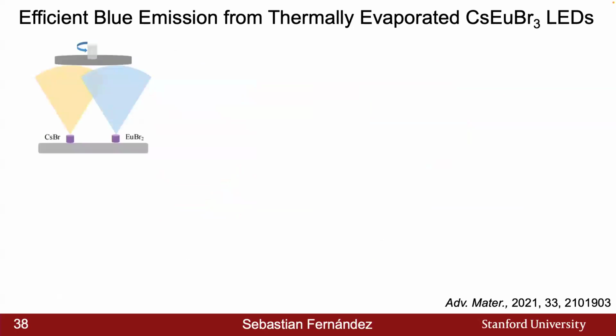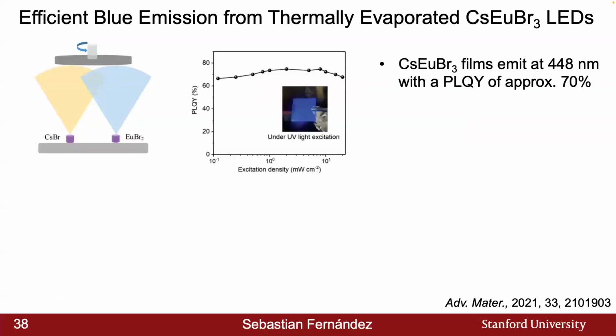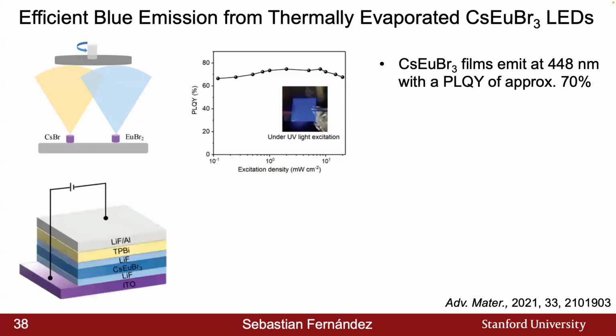And so additionally, now looking at the thermal evaporation of these rare earth element-based systems, previously workers had shown that by thermally evaporating cesium bromide and europium bromide together, it can lead to these deep blue thin films, which emit at around 448 nanometers. By integrating these perovskite thin films, the authors were able to land on this structure, which is a little bit different from the other structures that I've shown thus far, in which the perovskite layer is actually sandwiched between two insulating lithium fluoride layers. And this is because the perovskite layer itself wants to, oh, sorry.